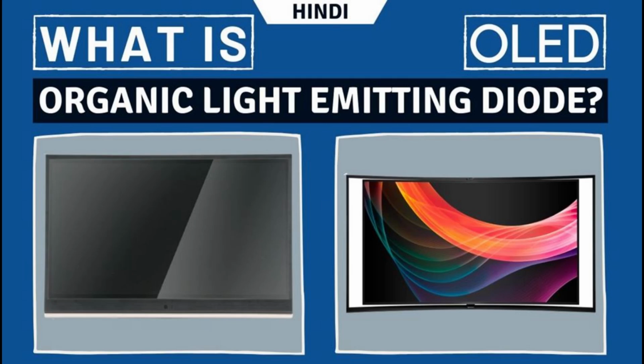Degradation occurs because of the accumulation of non-radiative recombination centers and luminescence quenchers in the emissive zone. It is said that the chemical breakdown in the semiconductors occurs in 4 steps. 1. Recombination of charge carriers through the absorption of UV light. 2. Homolytic dissociation. 3. Subsequent radical addition reactions that form pi radicals.